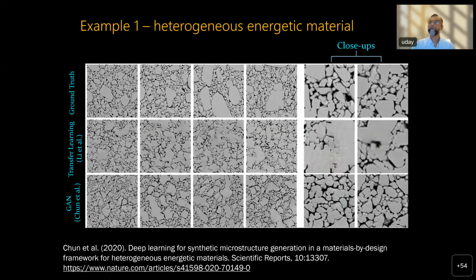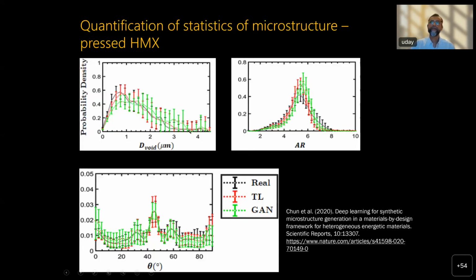As you can see, the GAN approach gives nice clean microstructures. The transfer learning approach can have some local glitches. These are close-ups of parts of this microstructure. And we found that GAN actually produces nice crisp microstructures that emulate the real microstructure. And in that paper, we also show quantitative comparisons of various statistics of these microstructures, showing that the black line here is ground truth, and these are probability densities of the void size, aspect ratio, and orientation of the voids.